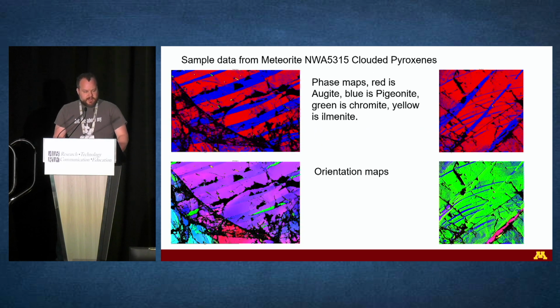This is recent work I did on a meteorite, NWA5315. These are known as clouded pyroxenes. The top maps, the red and blue ones, are phase maps. The red is a mineral augite, the blue is the fabulous mineral pigeonite, and the green is chromite, and the yellow is ilmenite. And this is what we were actually looking for, these little inclusion grains, and trying to see where they were and what orientation relationship they had to the other grains. We can see at the bottom we have orientation maps, so we can actually take this data and plot pole figures and look at the orientations in much more detail, but we can also just look at the pictures.